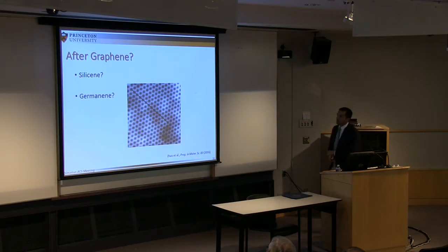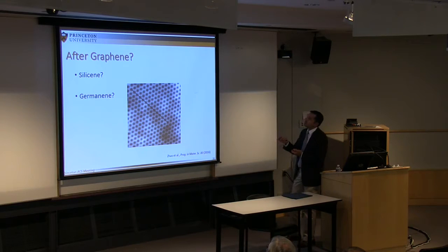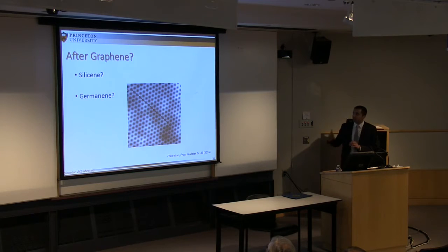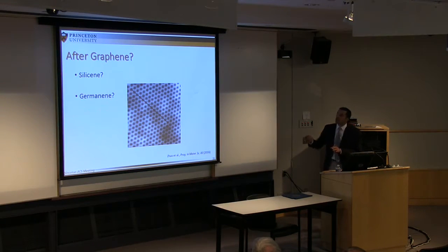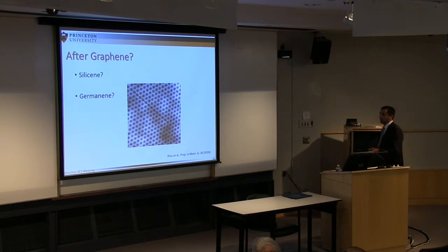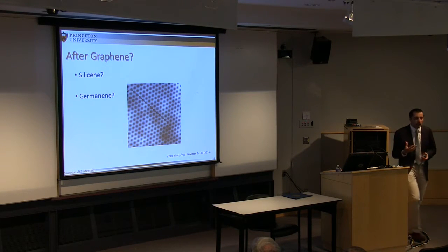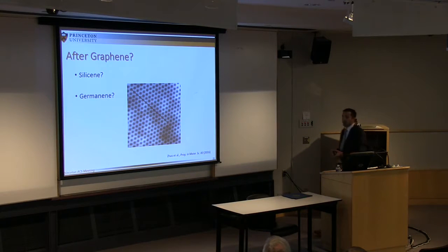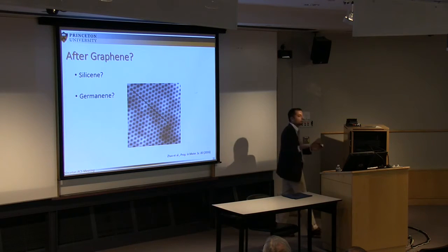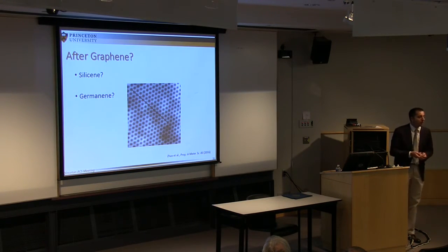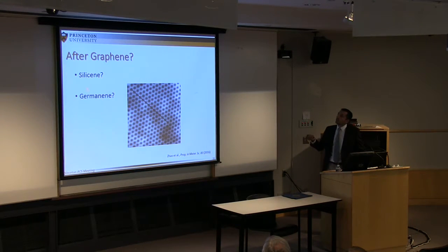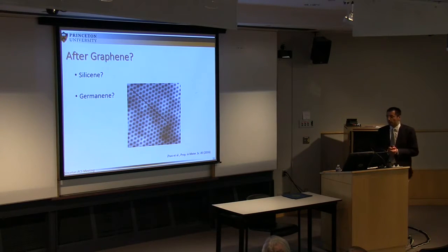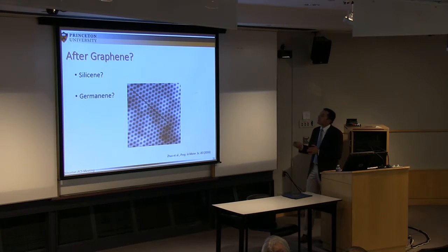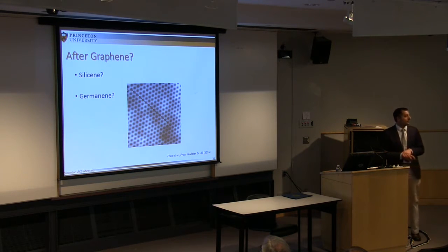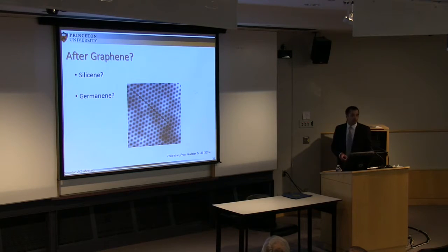For these materials, there are already simulations and also experimental measurements demonstrating that they can compete with graphene in terms of charge carrier mobility and also mechanical properties. The only issue here, and maybe it will be a trigger for further work, is the synthesis of these materials. You start with silicon, which is quite stable, then to synthesize silicene, you need to basically vaporize silicon onto a noble metal like silver or gold at extremely high temperatures and vacuum conditions. So, as we saw, because graphene made through mechanical exfoliation could not really go too far, I guess if there is a way to synthesize it, for instance chemically at larger scale, it may trigger a competition for graphene.